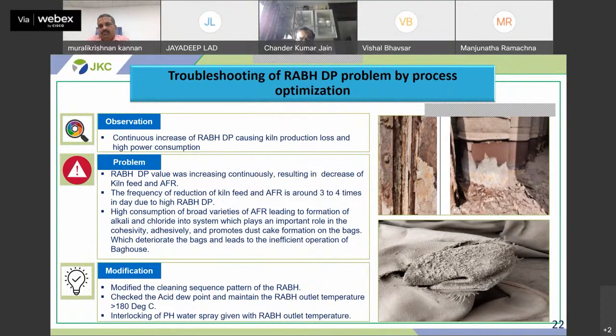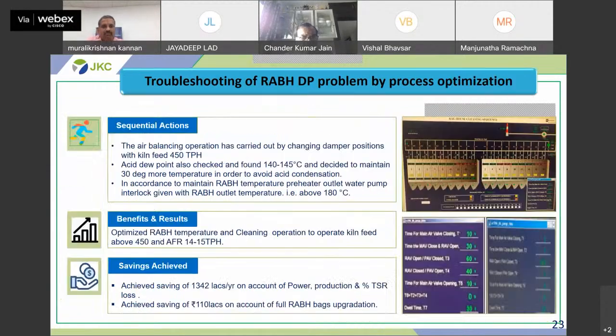As we are consuming a variety of AFRs, there was formation of alkali and chloride in the system, and it promotes dust cake formation on the bags, which deteriorates the bags and leads to inefficient operation of baghouse. Modifications made: modified the cleaning sequence of RABH cleaning pattern, checked acid dew point, and started maintaining RABH outlet temperature greater than 180 degrees centigrade in order to avoid acid condensation in the system. Interlocking of preheater water pump was given with RABH outlet temperature greater than 180 degrees centigrade.